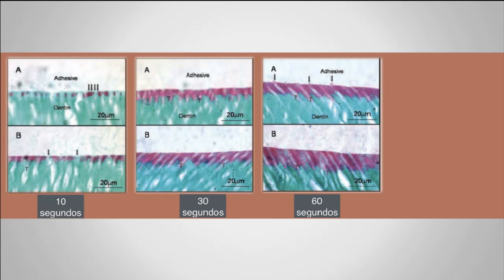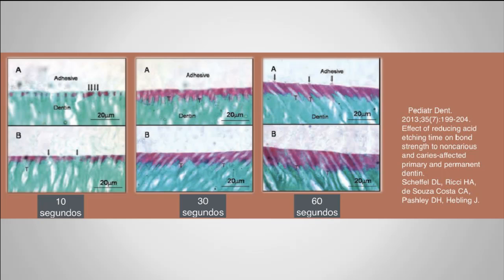In these images, you can see on the left side 10 seconds of etching on dentin, in the center 30 seconds, and on the right 60 seconds. In the red image, you can see the areas where you have a failure in the penetration and sealing of the dentin. This means that when you use too much time, you have a problem sealing all the depth that you promoted with the demineralization. So basically, I have one idea. We are etching the dentin too much. This is the first idea.